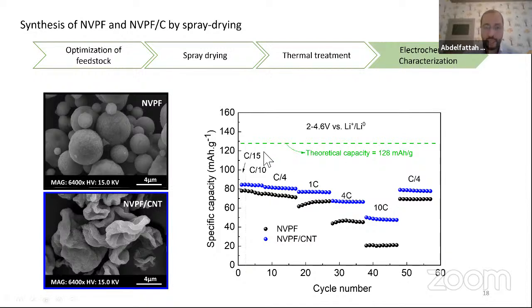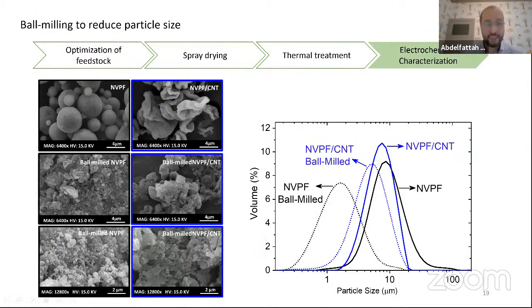But we can see that we are a bit far from the theoretical capacity, and in order to increase more the capacity of our material, we make the grinding of the particles in order to increase the surface area. And we can see after the ball milling, the morphology changed completely, and we formed agglomeration of the nanoparticles